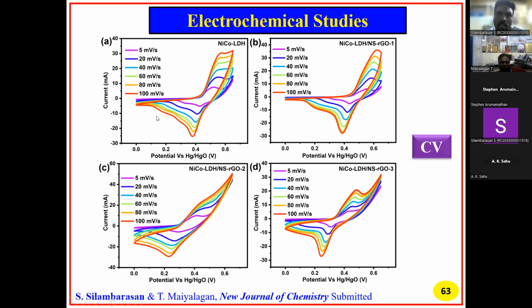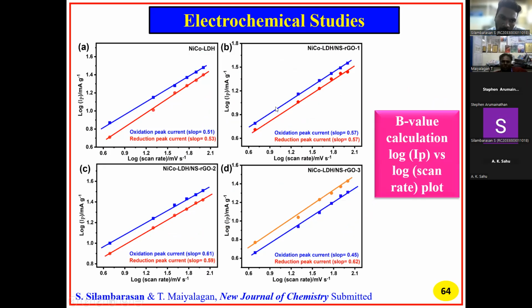Next, the CV. In CV, we applied scan rates from 5 to 100 millivolt per second. The potential range is 0 to 0.63 volt. From that CV, compared to the other samples, this sample shows more current, around 50. So it gives a larger oxidation and reduction peak area, compared across all these samples.